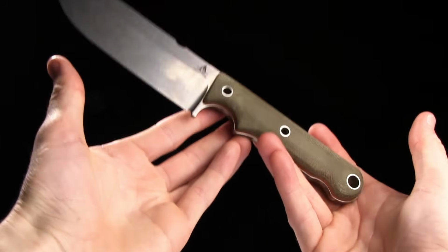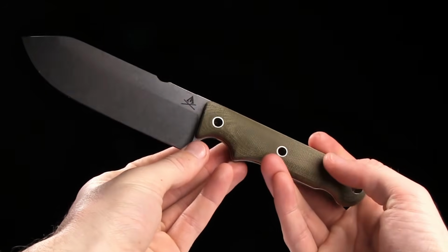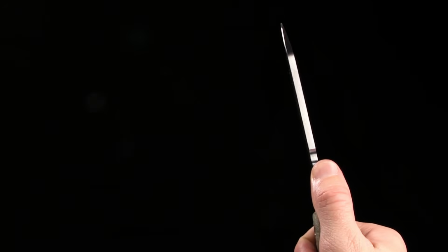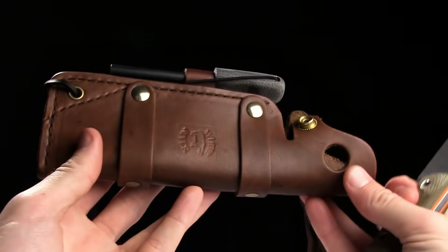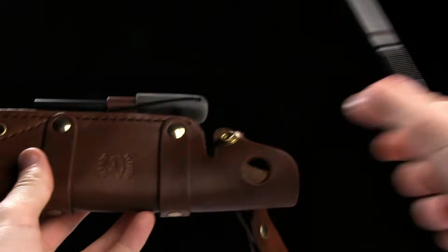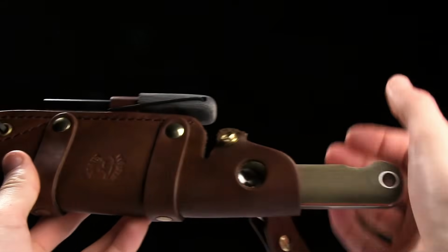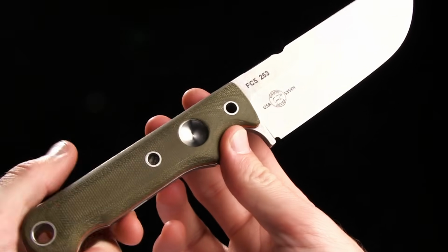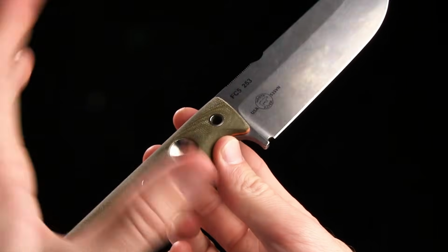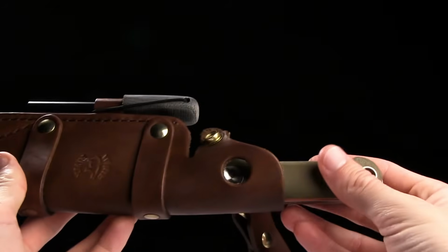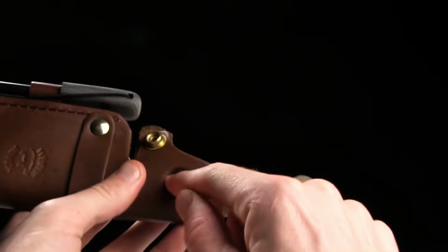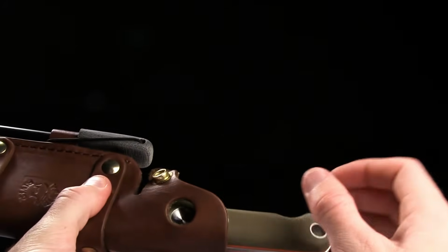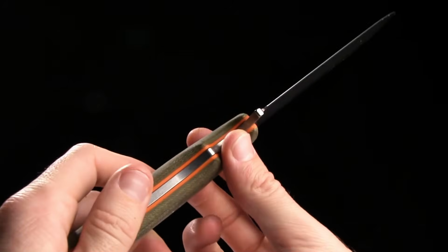The battening session produced a rolled edge after 40 minutes on frozen hardwood. Not chipping, not structural damage, a rolled edge that a field stone corrected in under 6 minutes. The prying test produced no tip deflection. The lateral stress test produced flex and return without permanent deformation.